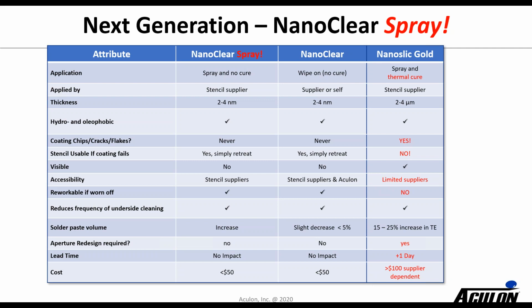And here we have some information comparing NanoClear spray and NanoClear to one of the main competitors out there, the Nanoslic Gold, which is an alternative traditional coating that is sprayed and then thermally cured. As you can see, both NanoClear and NanoClear spray go down extremely thin, 2 to 4 nanometers thick, which means that there's absolutely no impact on the aperture redesign. The alternatives are rather thick, so they do require an adjustment in aperture size. Unfortunately, because they're a traditional coating, the competitive coating does have problems in the field with coating, chipping, cracking, and flaking. And unfortunately, once that happens, the stencil needs to be discarded. Whereas with both NanoClear spray and the traditional NanoClear wipe, if that coating should wear off over time with use, they can very, very simply be retreated, or you can continue to use them in an uncoated state just fine.